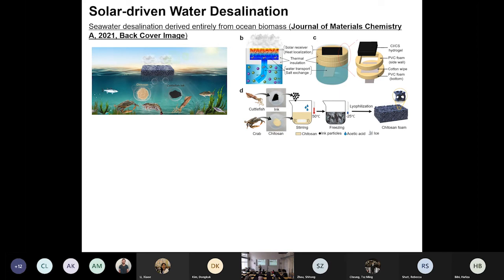So what are the black materials in the ocean, like cuttlefish ink? Cuttlefish ink is totally black. So we simply purchase some cuttlefish ink in liquid form, and we dry it. Also, in our lab we have a ball miller, so we're able to make carbon nanoparticles from the cuttlefish ink. The average diameter of the carbon nanoparticles we fabricated through the cuttlefish ink is only 10 nanometers. It's pretty good, and the raw material is cuttlefish ink.